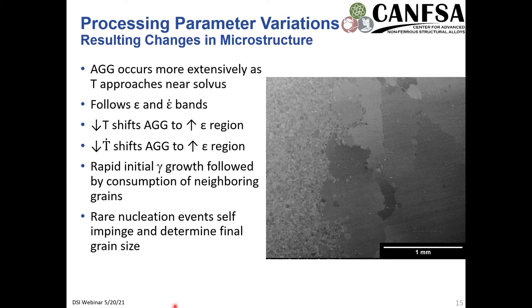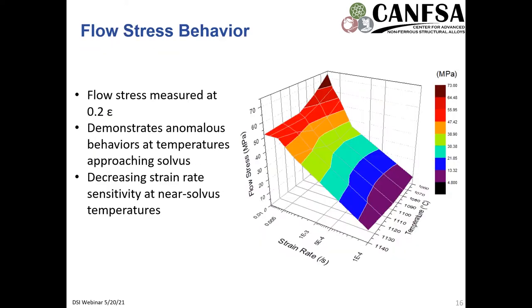We have this rare nucleation event of these abnormally large grains, and then rapid growth leads to a self-impingement of them upon each other, and that really determines the final gamma grain size. That is to say, if you have lower nucleation sites, you're going to have a higher final grain size. And so, exploring flow stress behavior, really looking at a set strain, we chose 0.2 strain, as this was a critical regime in the context of abnormal grain growth.